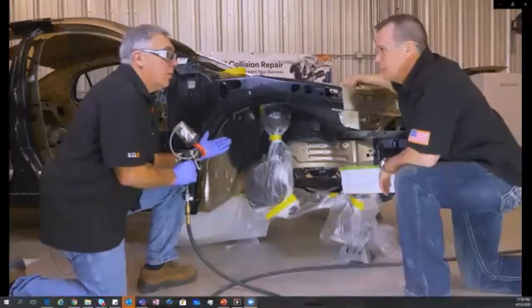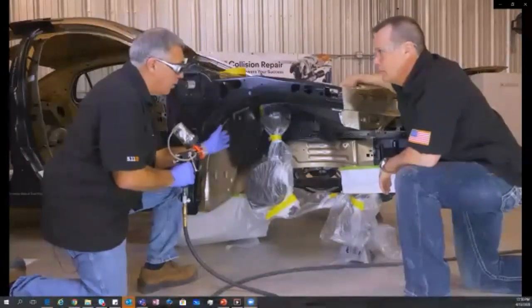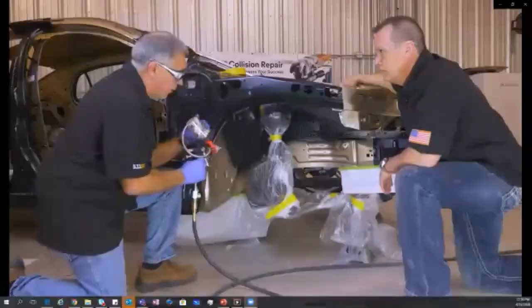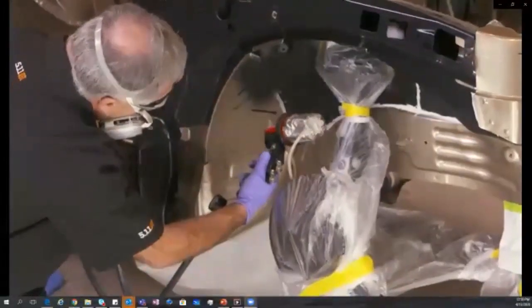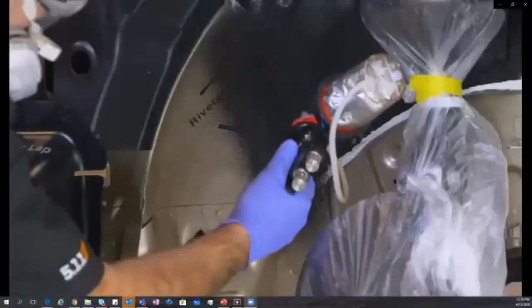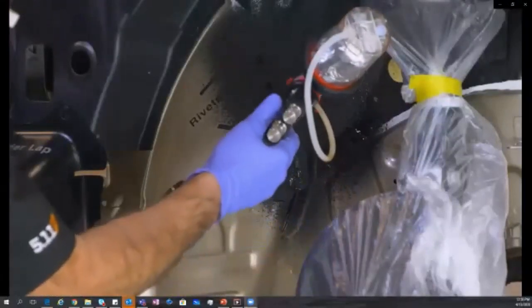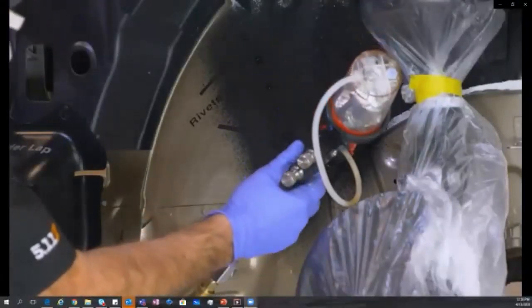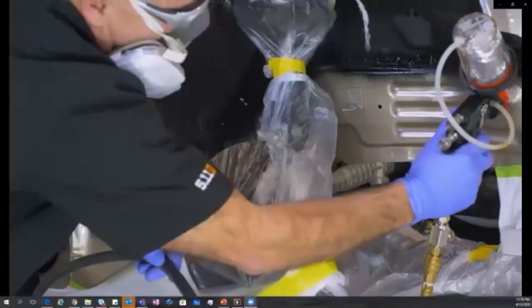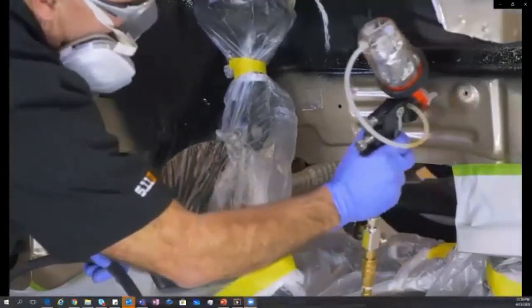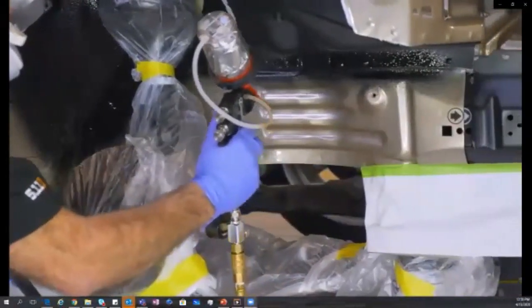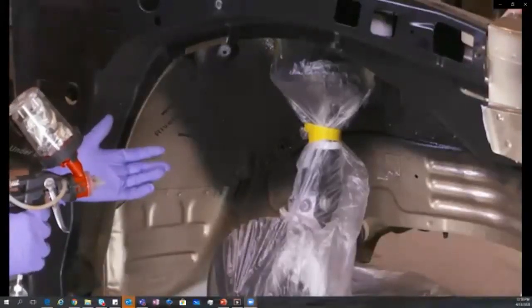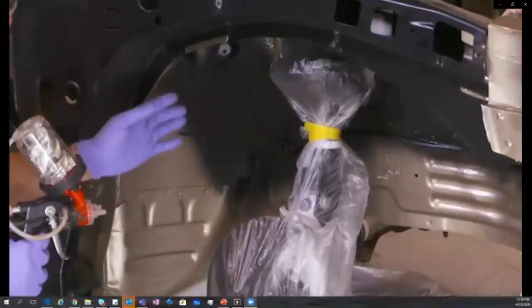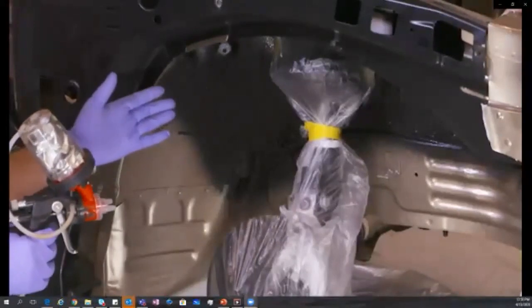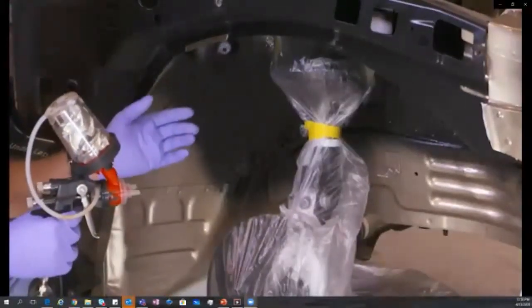But I know that GM is going to tell me that I need to put an undercoating on these outer panels. Now, this is a material that dries through a dry film, right? It's a rubberized material that dries dry. It's going to resist corrosion. It has a corrosion inhibitor in it, as well as it's going to stop stones from chipping through it, as long as I put enough of this material on. So I like to use about 2 to 4 coats. In this case, we put about three coats on here. And if I was to go four, I wouldn't feel bad about that because I know that more is better.